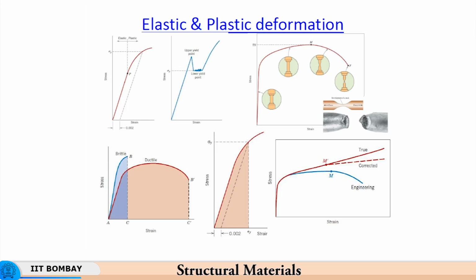the rate of work hardening becomes practically 0, and that is because you have a process called dynamic recovery, which results in the dislocations arranging in specific configurations, in low energy configurations, due to which you have subgrain boundaries which are generated, and there is no further work hardening possible.